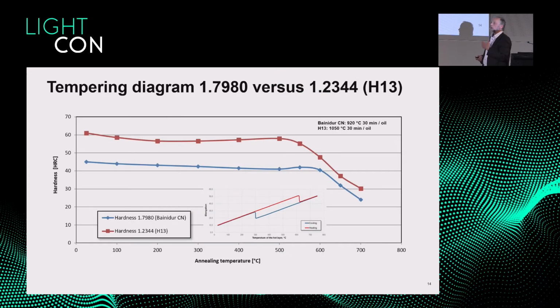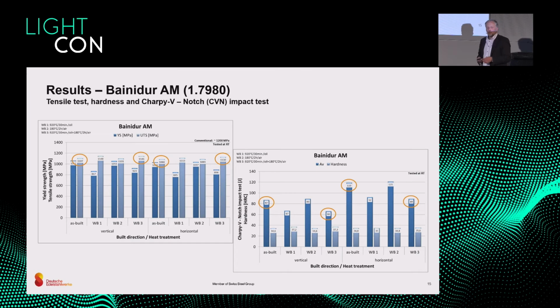In this point, I claimed the idea is to improve the additive manufacturing process by a steel with an austenite martensite or bainite transformation to have a lower hardness. You compare the blue line, that's a new steel, with the standard tool steel, in this case a 2344, and you see over the complete temperature range you have a lower hardness, and this should improve the additive manufacturing without cracks, because you have a lower hardness and you allow some kind of micro deformation, and you will reduce the risk.